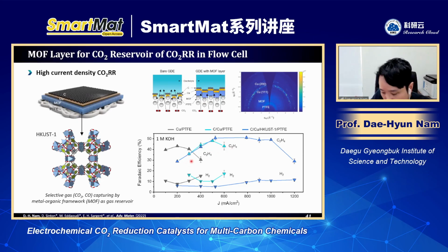The reason why it is very difficult to increase the partial current density can be understood from this graph. For example, in the case of bare copper PTFE GDE, there can be an optimal potential or current density where we have the highest FE for ethylene. But if we keep increasing the potential, we see an increase of hydrogen and a decrease of ethylene. This is because of limited CO2 mass transport in the GDE. But if we enhance this, then we can maintain the selectivity up to high current density, and this will increase the partial current density for these products. So this MOF is also very effective for CO2 mass transport.